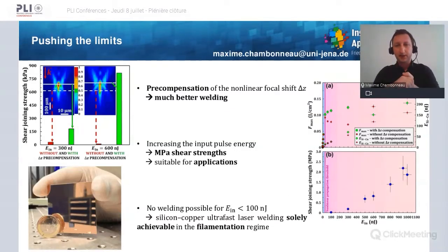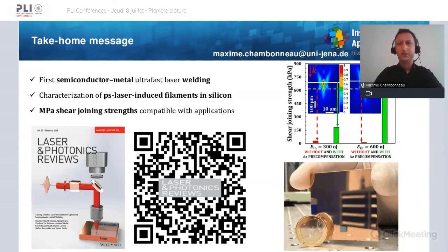The reason for this success is that precompensating the nonlinear focal shift leads to an enhancement of the maximum fluence as well as the energy reaching the interface. Noteworthy, as illustrated here by this purple line, there is no welding possible for input pulse energies below 100 nanojoules, meaning that silicon to copper ultrafast laser welding is solely achievable in the filamentation regime, meaning that it's really important to measure and precompensate the nonlinear focal shift in the end. So here is the take-home message for that part. We have achieved the first semiconductor to metal ultrafast laser welding by characterizing picosecond laser-induced filaments inside silicon.